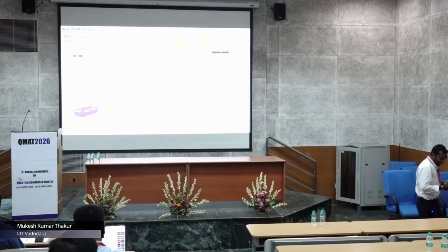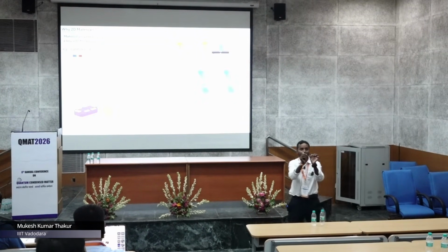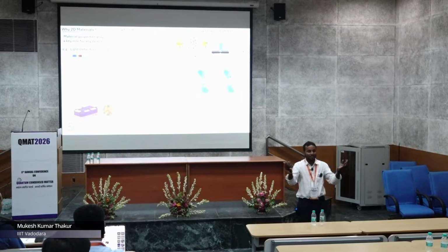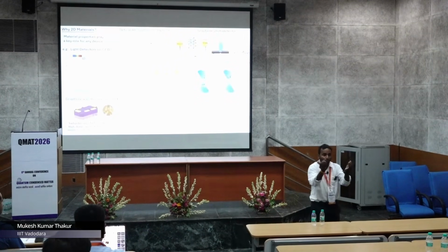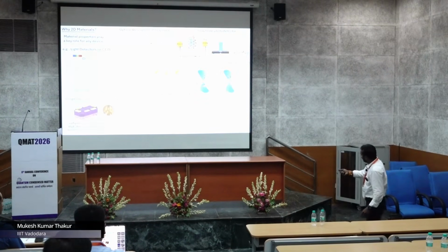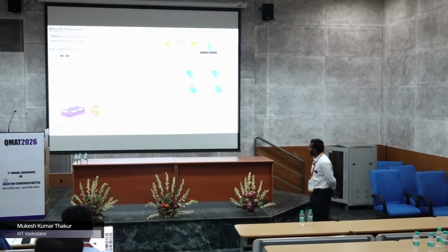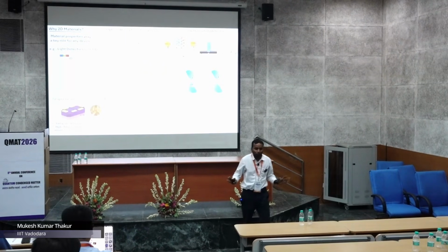So what is the issue? The main reason was carrier recombination. When you shine light on graphene, the carriers create electron-hole pairs, but they recombine within picoseconds or femtoseconds, so even by applying a voltage you cannot separate them. But you can integrate graphene with silicon very nicely. Now you see graphene and silicon, and you can see a very nice photocurrent. So integration is possible, right?